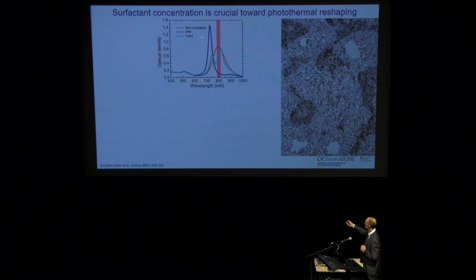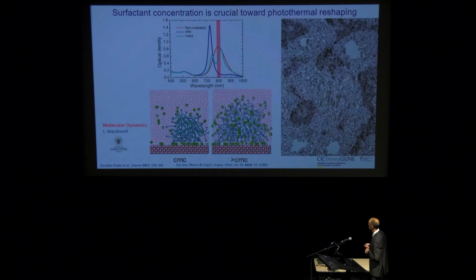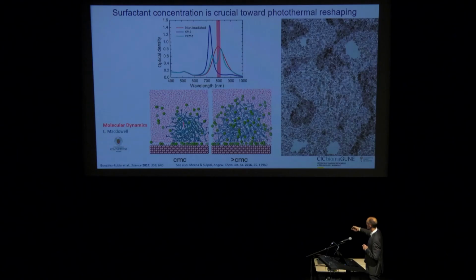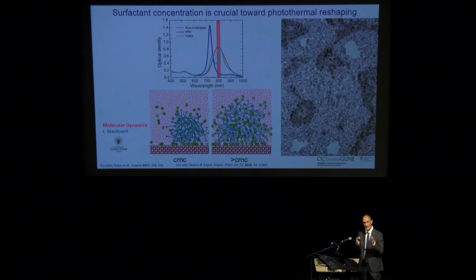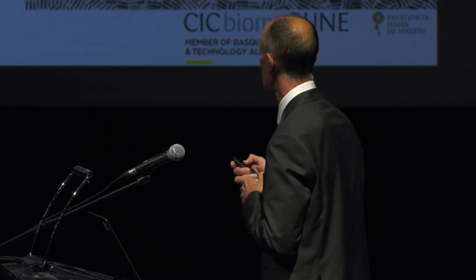If you are using a much higher concentration of surfactant, then you obtain a bimodal distribution because this effect is not so well controlled. And so our argument to explain this is that close to the critical micellar concentration, the bilayer is incomplete, in agreement with the measurements by Olivier, while at higher concentrations it may become more complete. So in this case, part of the energy that you're injecting with your laser into the particles can be released to the solvent quickly enough, while here it gets accumulated and protected inside the particles, so the reshaping will be less controlled. So anyway, this is one of the ways to make very highly monodisperse nanocrystals.